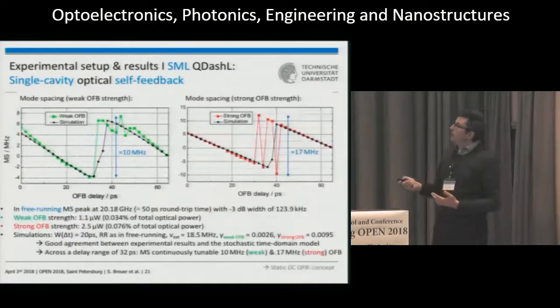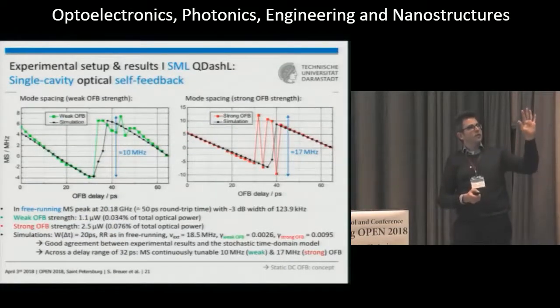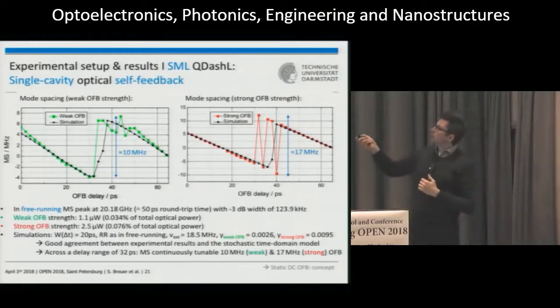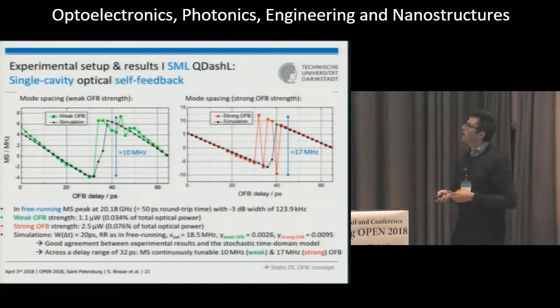And if you compare this result, so this is just a change in the mode spacing, which is dynamically possible through the optical feedback delay. This is the optical feedback delay. It's possible to change this mode spacing dynamically and also reproduce it with the simulations, which are in black, quite nicely for strong and weak optical feedback.